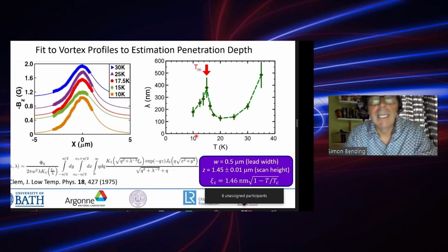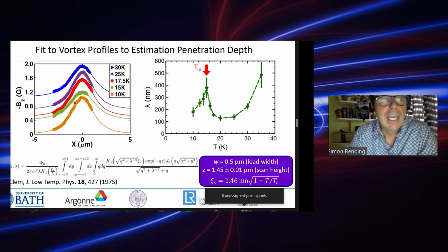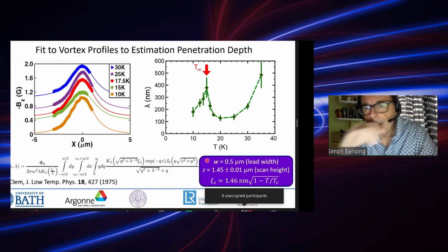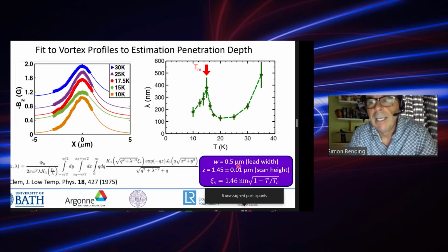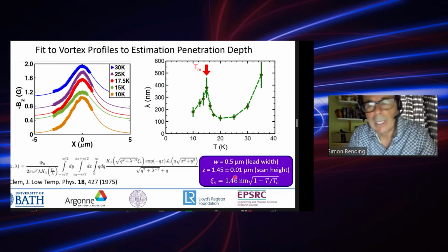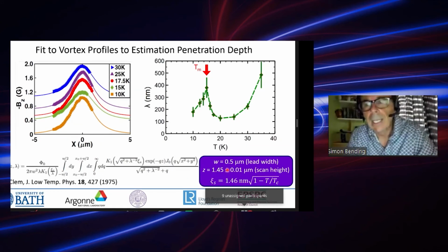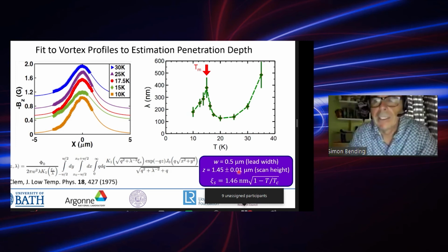Now we can do a much more quantitative job of analyzing this data if we fit these data to a model. And the model we choose is a modified version of one that was developed by John Clem many years ago. The formalism is quite standard and straightforward, but there are three main fit parameters that enter into this theory, one of which is the lead width of the Hall probe that we're using. In this case, it was about 0.5 micron. Another, which is not so important, is the temperature dependence of the superconducting coherence, that actually doesn't enter very significantly into the modeling. The most important one, in fact, is the scan height, the height at which the active sensor is scanning above the surface of the superconductor. And in this case, we find it to be about 1.45.